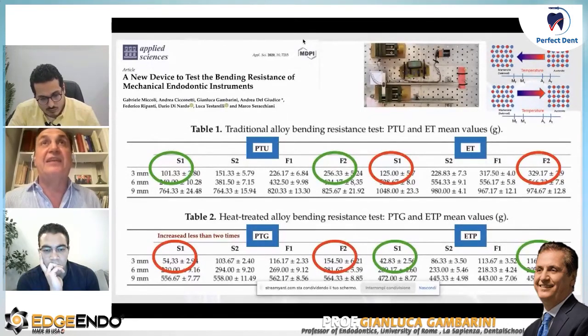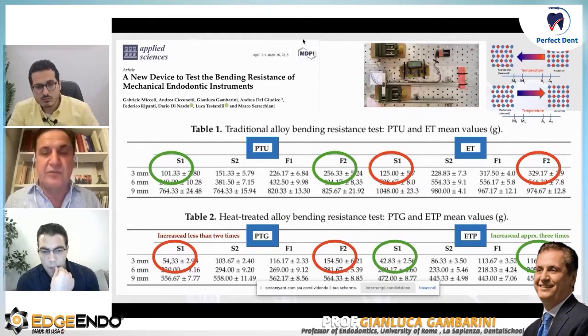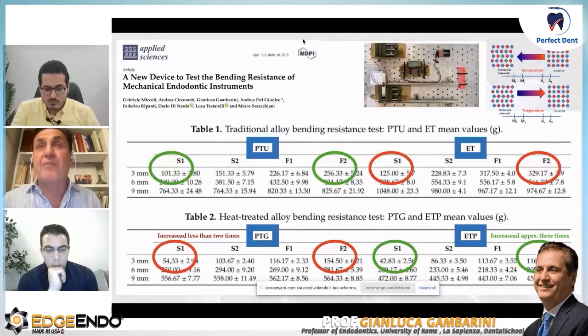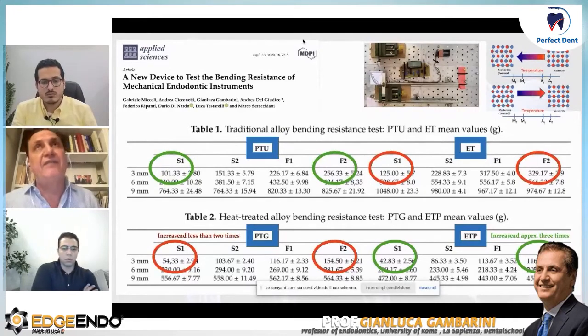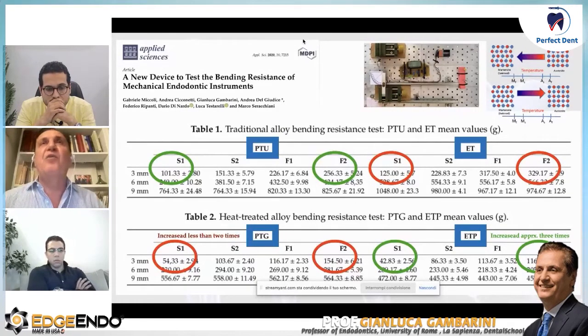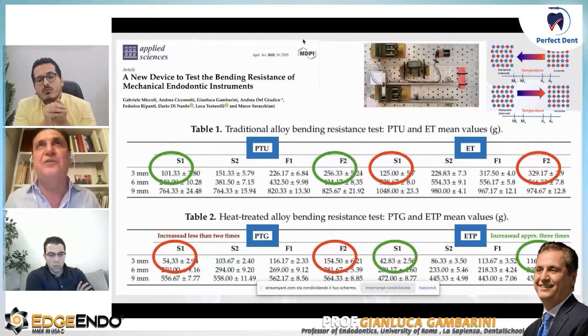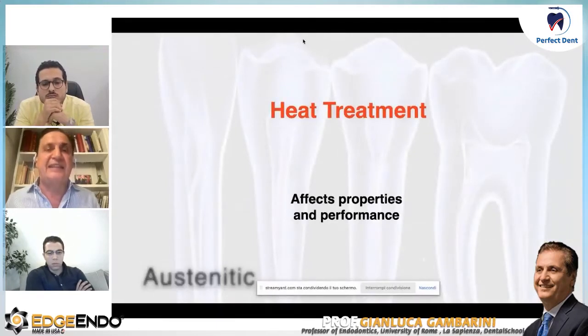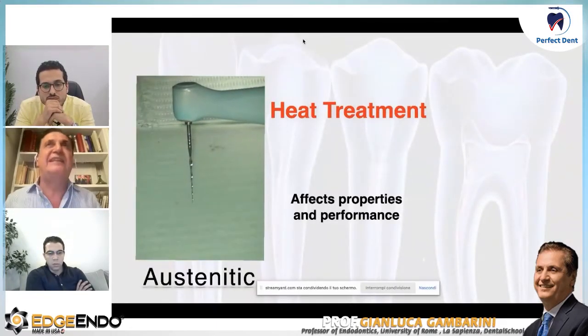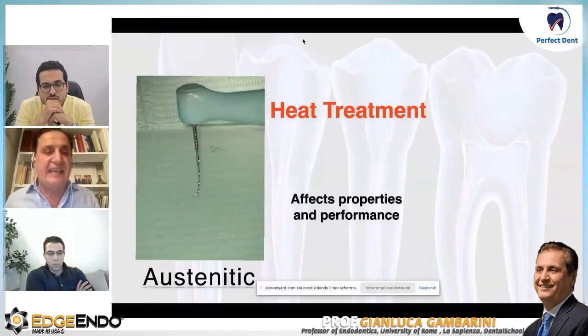And if you want a little bit more data, with the Dense ply treatment, we can increase the flexibility a little bit less than 2 times. With the FireWire, we increased the flexibility of the file approximately 3 times, which is a huge improvement. So when we speak about management of an apical curvature, we have to understand that these are the same instrument in the design. We may do something very different if we use an austenitic, more rigid, traditional file versus a new, more flexible and ductile martensitic file. As a matter of fact, the heat treatment does affect performance quite a lot.